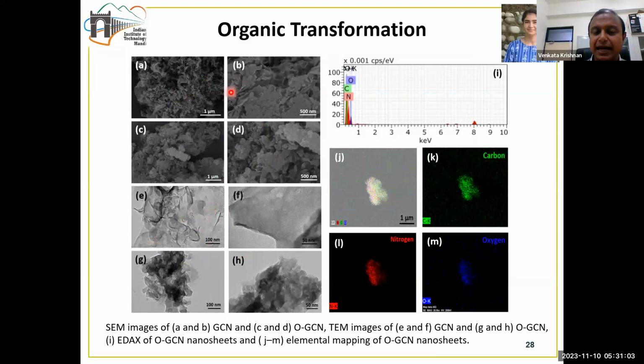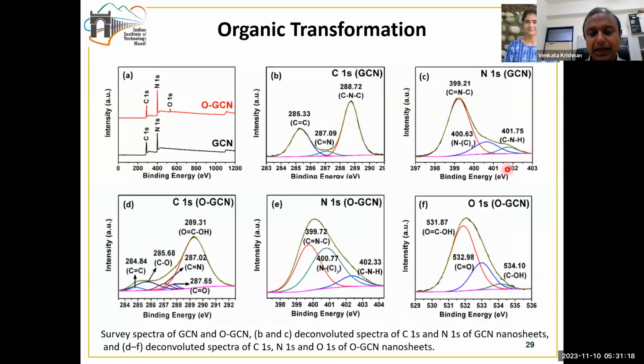SEM stands for scanning electron microscopy, and TEM stands for transmission electron microscopy. And this, coupled with the elemental mapping and the EDAX, provides a lot of valuable information regarding the morphology and also the elemental distribution across the sample. Then we did a very detailed analysis of the sample using XPS spectroscopy, which indicates how the different elements are interacting with each other, what the oxidation states of the different elements involved are, and what the surface composition of the elements present in the material is.